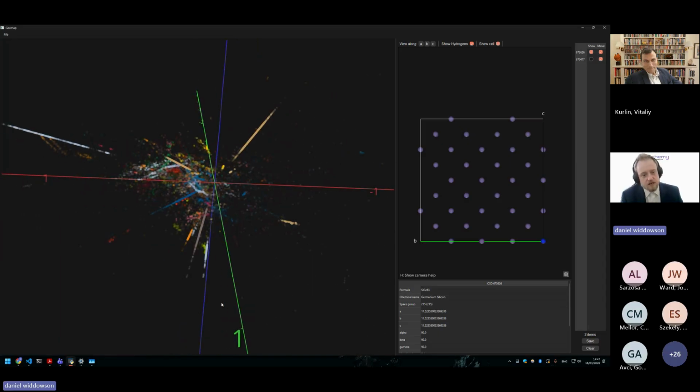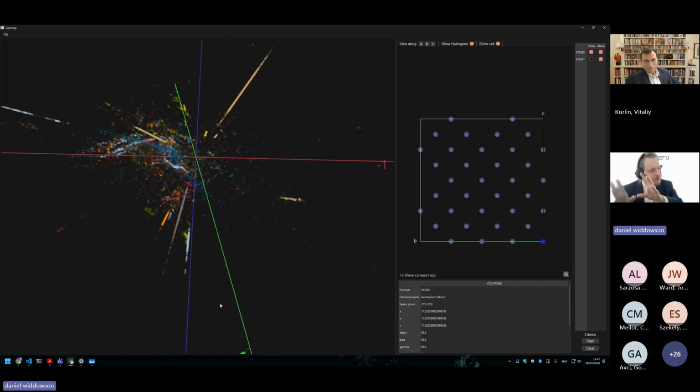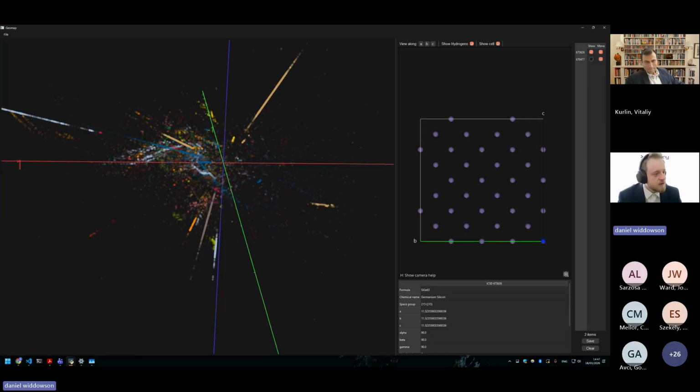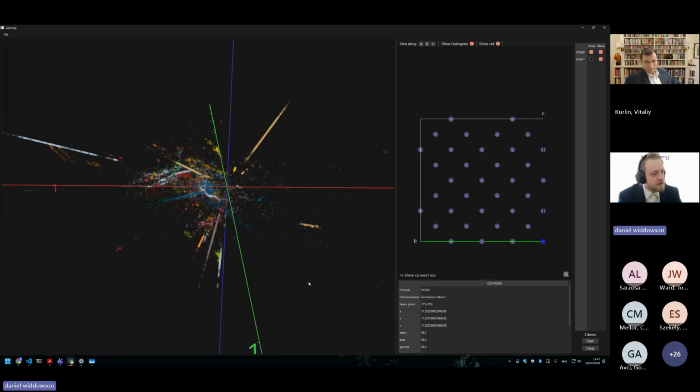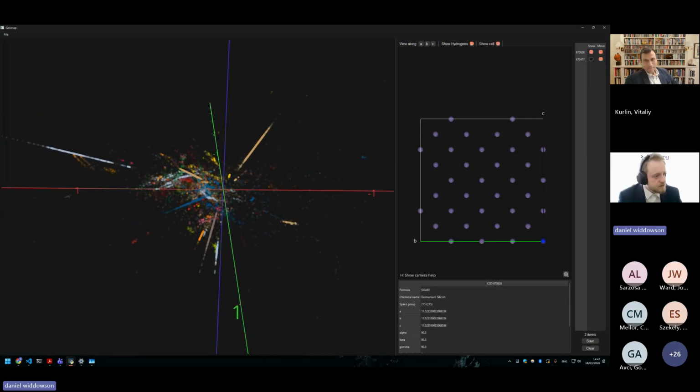So some of these lines, where this all should be cubic crystals, where the three unit cell lengths are identical, there are some where they're just a little bit off, so it shouldn't be cubic, but the symmetry analyzer says it's cubic because there are tolerances. Well, if I keep deforming that structure and I keep changing the cell lengths, at some point the symmetry analyzer is going to tell me, oh, you're not cubic anymore. But the whole time it was one smooth deformation, and that's realized in this space. So with that, let's look at something else.